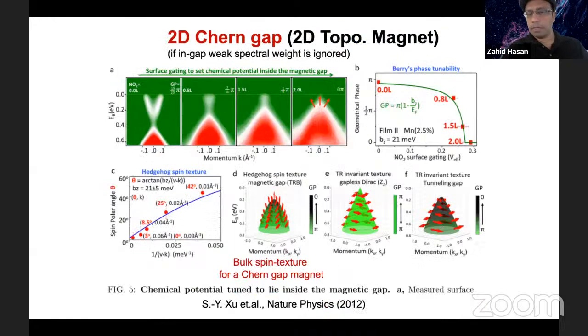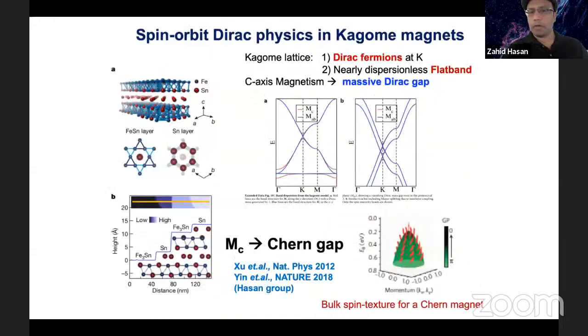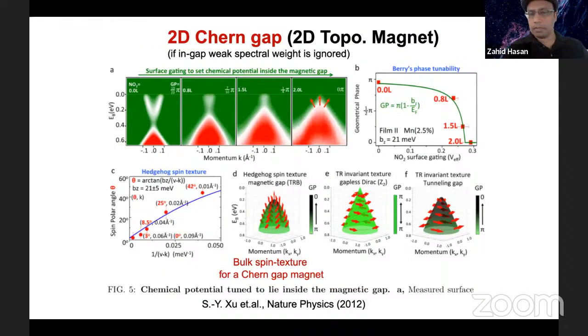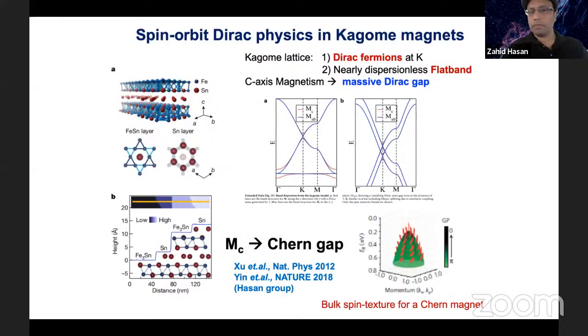Okay, so once we have these experimental procedures to tell whether you have a Chern gap or not, we could explore other materials that are cleaner. Magnetically doped topological insulators turned out to be very complicated. So then we moved to other cleaner systems without doping, naturally magnetic, for example, Kagome magnets. The Kagome lattice has the interesting thing that you have a Dirac fermion at the K point, and you also have a flat band. This is before twisted bilayer graphene. We were trying to think how to bring flat band and topological physics together in a single system so that you could probe the interplay between topology and strong interaction.